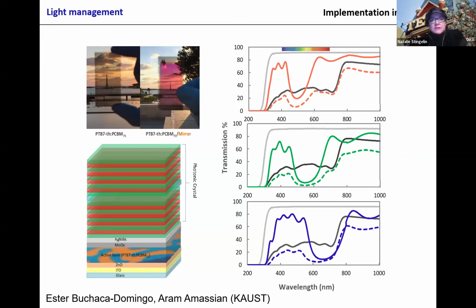Well, if you stack them, you get there. And again, it's not only about the efficiency. I think the key thing for the organic solar cell is really that they're semi-transparent, as this picture here showed. So you can integrate them in greenhouses, and the plants still grow. This would be impossible with silicon solar cells. So I would not say polymer solar cells or metal halide perovskites compete with silicon, because efficiency is maybe not fully there, but it's not only about efficiency either. A good example for polymer solar cells is the integration in greenhouses.